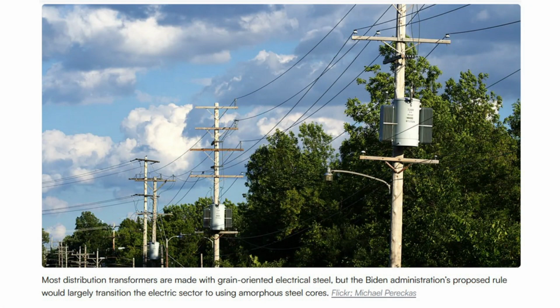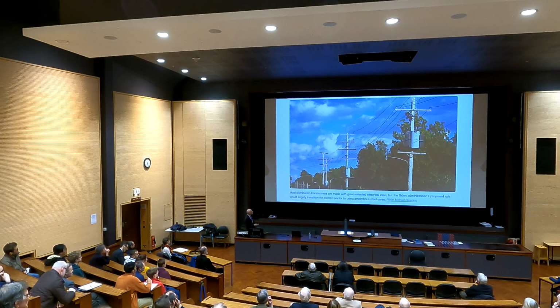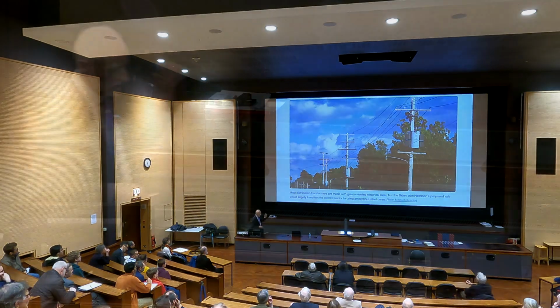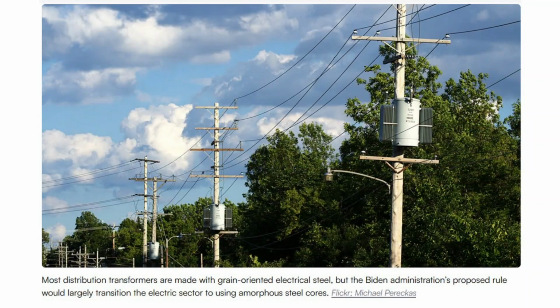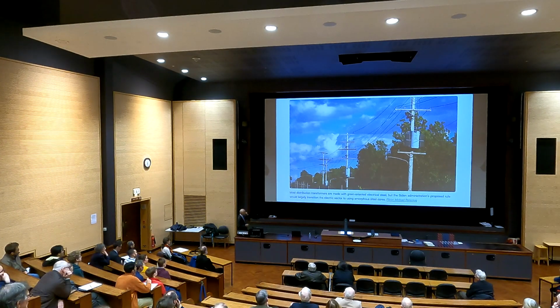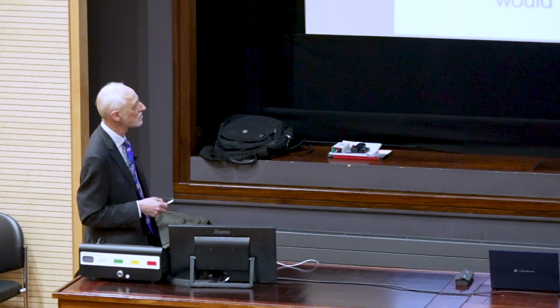Where they're more obvious would be like this. So this is a rather awful looking sort of distribution system for electricity that you would typically find in the United States and Japan, not in Europe. These are the local distribution transformers, changing your voltage down for local use, and they have these cooling fins. They need the cooling fins because the transformer core inside dissipates a lot of energy. And it's because the grain-oriented electrical steel isn't as good as it should be in allowing you to keep switching the magnetic field direction, magnetic moment. So there's a lot of energy lost in these. This is the material, grain-oriented silicon steel.